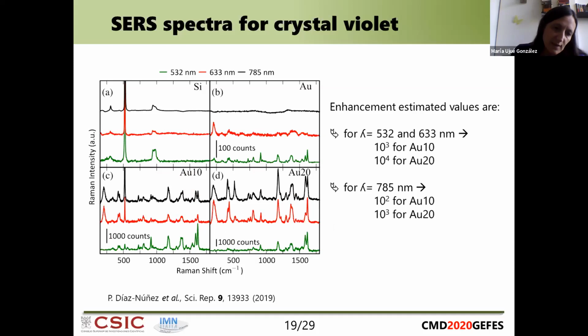So the system is actually working, and we did an estimation of the enhancement we were obtaining, that is not so easy to do because it's difficult to calculate how many molecules are really getting inside on top of the nanocolumns. But more or less we could estimate that for the short nanocolumns we had 10 to the 3 enhancement in the lower wavelengths, and for the long ones it was an order of magnitude bigger.